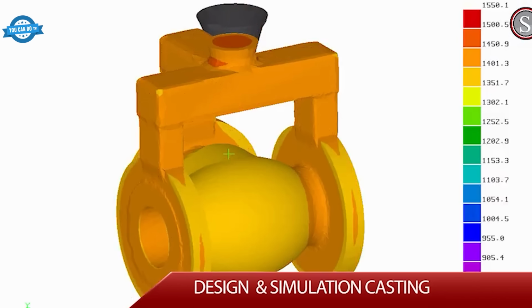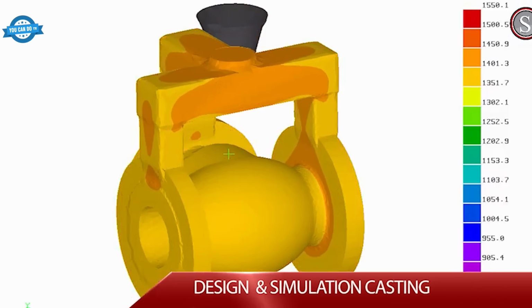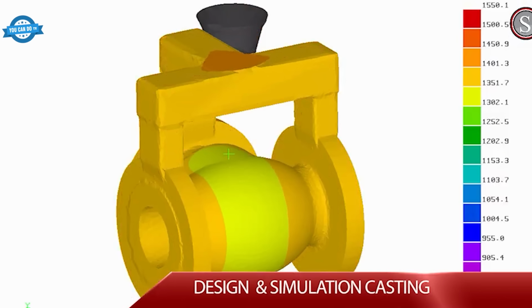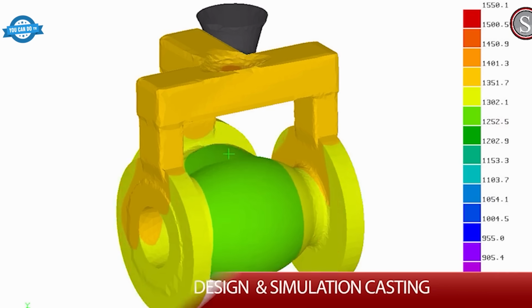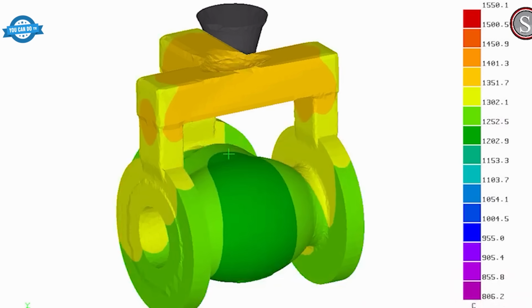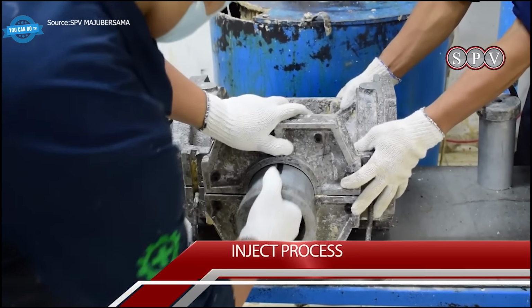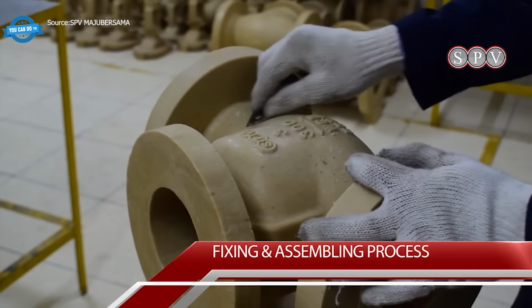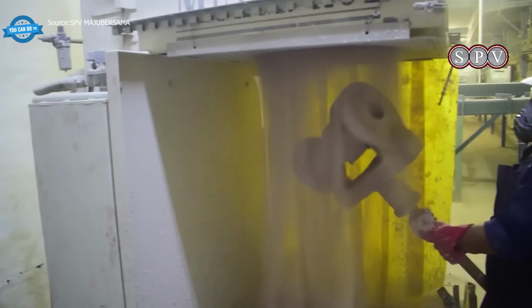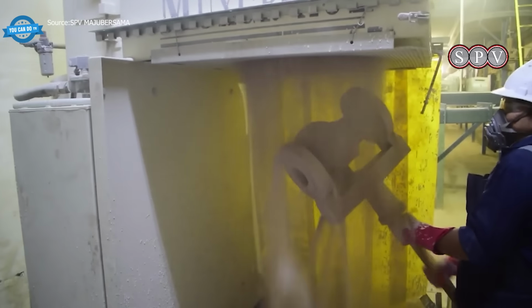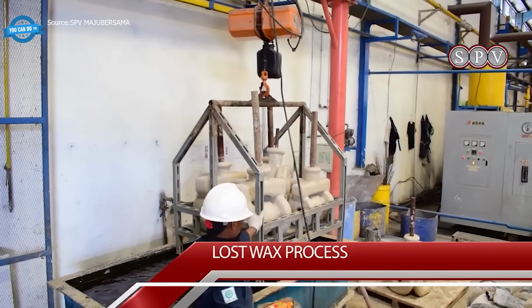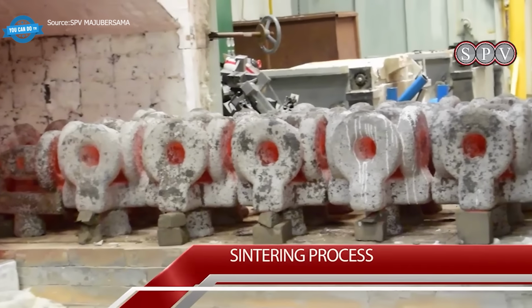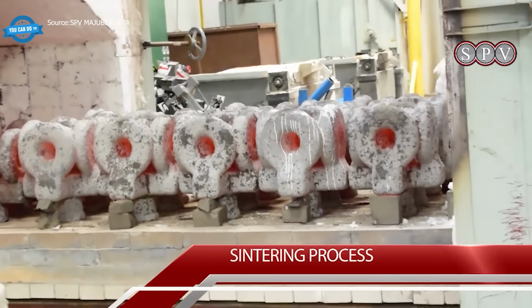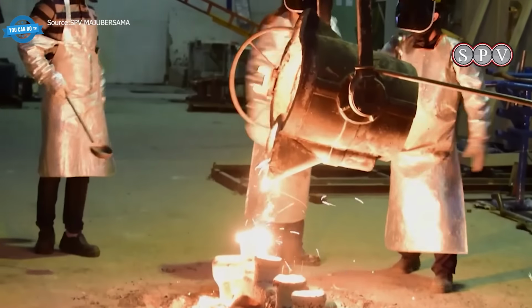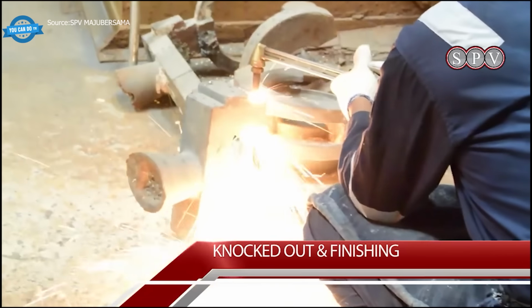Behind that simple brass fitting sits a far more demanding process for the valves running inside oil and gas systems. Industrial valve casting begins with simulation software modeling thermal behavior before any metal is poured. Wax patterns form the casting template, dipped repeatedly into ceramic slurry to build a shell, then melted out in hot water baths. The hollow shells sinter in furnaces before molten alloy fills them.